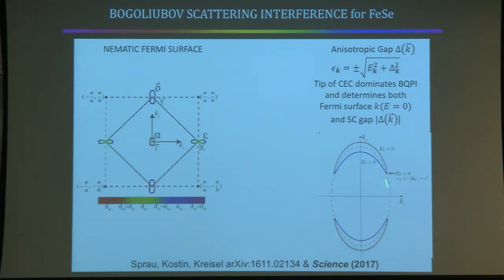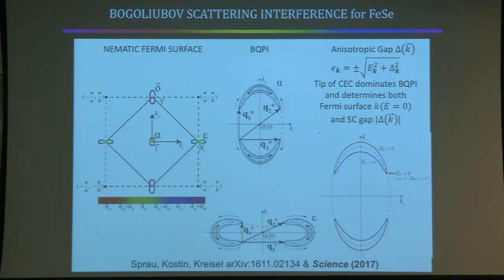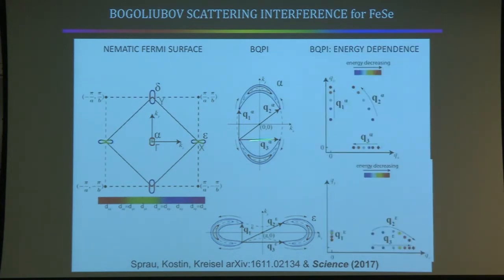The joint density of states from scattering dominates the interference. So if you put an impurity into a compound in this situation, and you measure the scattering interference at this particular energy, you'll see three predominant scattering vectors here, there, and there. And similarly, I could make the same argument for this band. If it has a highly anisotropic gap, it would have three predominant scattering vectors. Furthermore, if you had a model for the gap as a function of momentum, then you could predict what happens to these scattering vectors as a function of energy. That's a natural property. Yes?